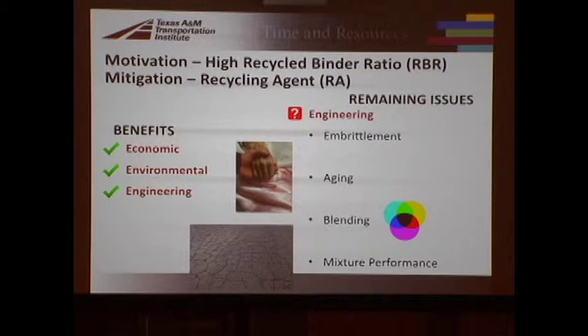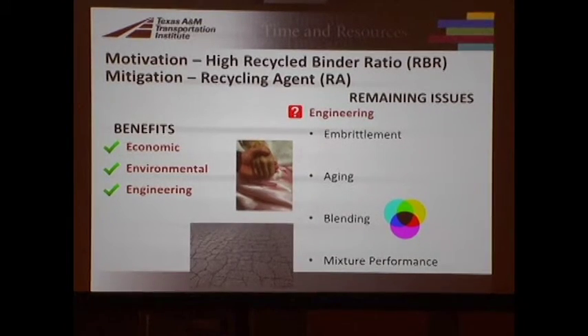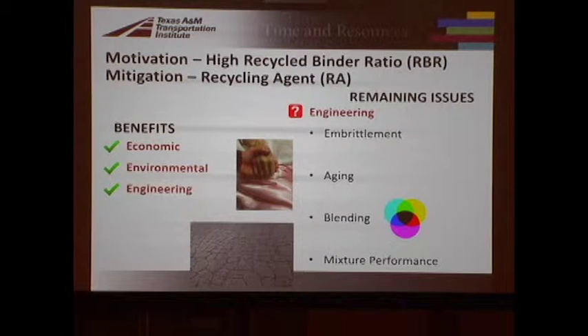As we all know, the motivation of increasing the recycled binder ratio, or the RBR, is economic, because we don't have to use as much virgin material, environmental, because we're recycling materials, and there are some engineering benefits. But when we get those RBRs too high, we have some issues. The material is too stiff and too brittle. We also don't really know what happens with these mixtures with respect to aging. There's also a big challenge in terms of blending. What is the actual blending occurring between the virgin binder, the recycled binder from the RAP and the RAS, and any recycling agents we add? And finally, the mixture performance, especially with respect to cracking. That's what we're worried about, because we have these stiff, brittle mixes with high RBRs.